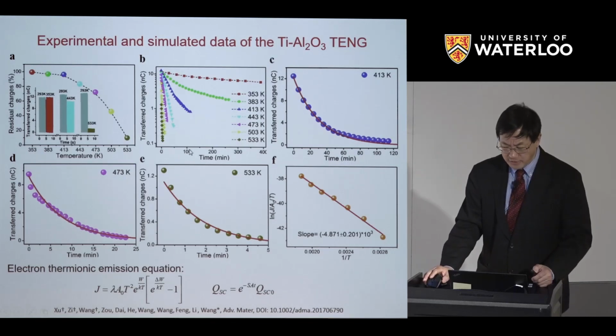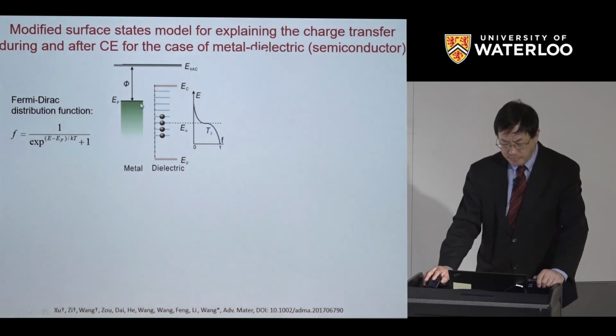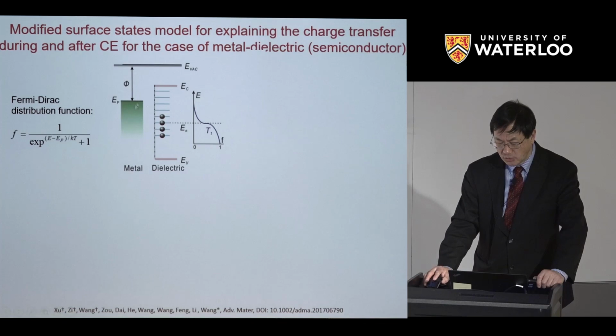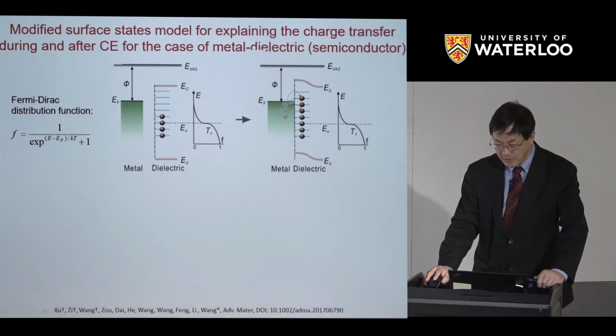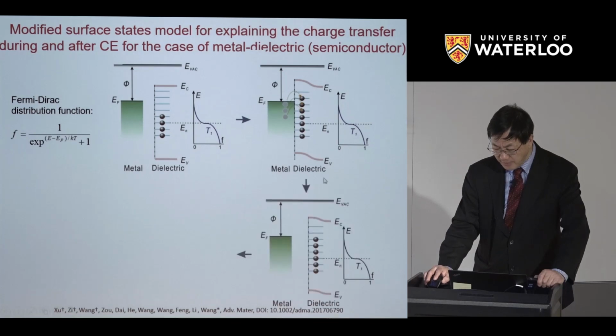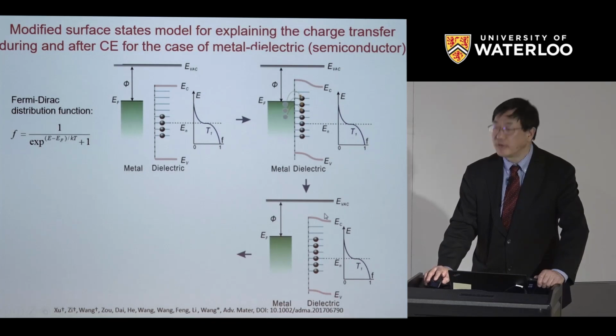So through those studies, what do we find? Let's look at the first case here. We have a metal and a semiconductor or dielectric case. The two are separated. And this is the distribution of electrons around the Fermi level here, and this is given by the Fermi-Dirac distribution function. If you bring the metal and the dielectric into contact here, because the surface states here have a lower energy, the electron will transit from here to here. Electrostatic charge goes here. But now, if you separate the two, because those electrons are located lower than the Fermi level on this side, in order to go back, they have to overcome a barrier, so they remain in the dielectric. So this becomes electrostatic charge.